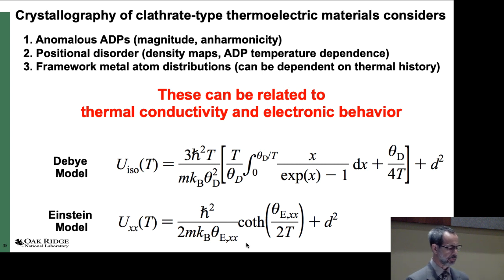So when you consider the crystallography of clathrate-type thermoelectric materials, there are 3 points. The anomalous ADPs, their magnitude, possible anharmonicity, the positional disorder, which you can see in density maps, and also the temperature dependence of the ADPs. But a third thing that is also important is that the framework metal atom distribution needs to be determined. This can be dependent on the thermal history, for instance, how gallium and germanium partition on the 3 different sites in the clathrate structure.